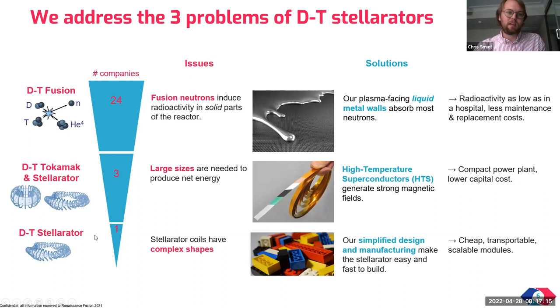First of all, the deuterium tritium fusion reaction creates neutrons, and these neutrons can activate the solid part of the reactor. So the way that we mitigate this is with stabilized liquid metal flow against the inside wall that will absorb most of the neutrons. And the goal is to achieve radioactivity as low as in a hospital, long lifetime. So liquid metal will be coating the inside of our reactor.